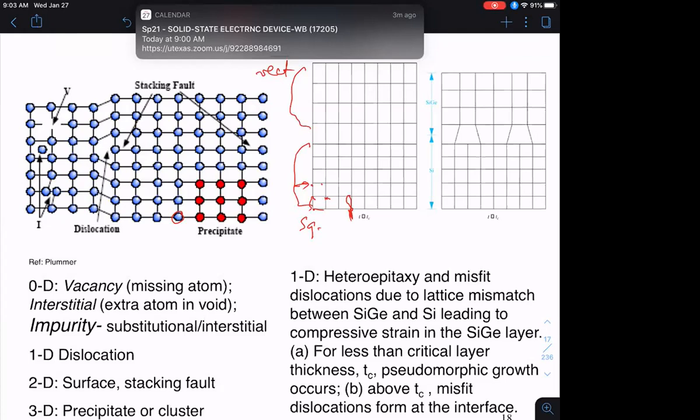And the principle is very simple. So you always work in terms of, let's say, the unit cell, okay, which in this case is this square. So how many atoms belong to this unit cell? So if I focus on, say, this particular unit cell, I see that I have 4 lattice points at the corners, but only 1/4 of each of those points should be counted towards this square, right?